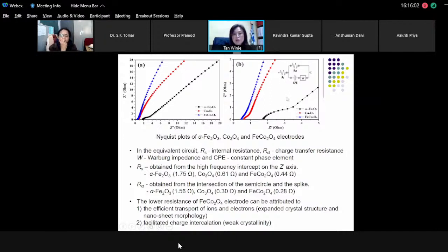So how do we get RS, the internal resistance? The intersection at the high frequency on the Z prime axis will give the value of RS. Then the charge transfer resistance RCT is obtained from the intersection of the semicircle and the spike. This spike represents the Warburg impedance, which describes the ionic diffusion at the interface between electrolyte and electrode. So we obtained the RS values: for hematite, we have 1.75, cobalt oxide 0.61, and iron cobaltite the lowest at 0.44 ohm.